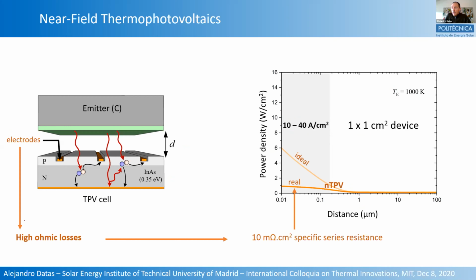So if you incorporate typical ohmic losses for these electrodes of 10 milliohm square centimeter, then you get this real performance of the near field TPV device. So you see that you lose quite significantly the capability of increasing the power density. So this points out a problem of scalability for near field TPV devices. I want to remark that I have made this for front side electrodes, but this will apply also if you make the electrodes on the rear, because at the end, the problem with the ohmic losses is the lateral conduction. So this trajectory of the minority carriers, when they have to travel to the local electrodes, is the main contribution to the ohmic losses, together with the conduction, of course, through the metal grid.